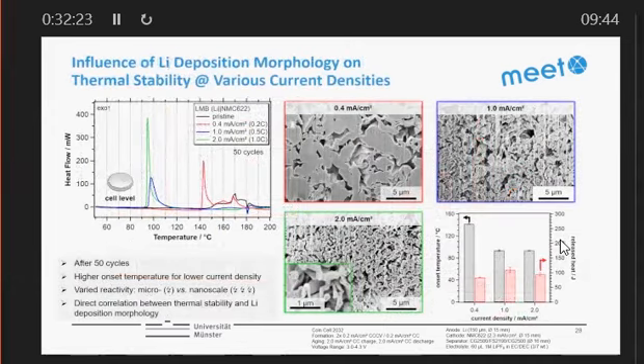So then we look at the lithium deposition morphology at different current densities before we had cycle number, and we see that the higher the current density, the more problems. This is as expected, but had to be systematically investigated. And we see also that the onset temperature goes down when we go up with the current density. And basically, we see that the threshold is typically at less than 0.5 C. That's the threshold where in liquid electrolyte, you get reasonable deposits for lithium metal. Beyond that, you already are getting a lot of high surface area lithium.